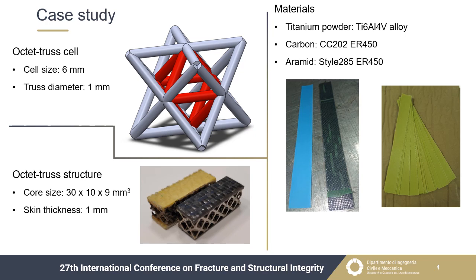The titanium powder adopted in the present research activity was made of the titanium-6 aluminum-4 vanadium alloy. As concerns the skins, two different types of fibers were taken into consideration, carbon and aramid. All the prepreg had the same epoxy resin as matrix.